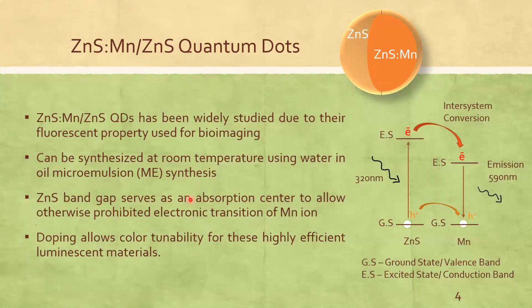The manganese by itself does not give fluorescence because its electronic transition is prohibited. So doping it inside the zinc sulfide, which serves as an absorption center. When UV light with 320 nanometer wavelength hits the quantum dot, an electron is excited from the ground state to the excited state in zinc sulfide, and it creates a hole in the ground state. This hole moves to the ground state of manganese, and the excited electron jumps to the excited state of manganese. When this excited electron relaxes back into the hole, it emits light with 590 nanometer wavelength, which is an orange color emission. So doping allows color tunability for these highly efficient luminescent materials.